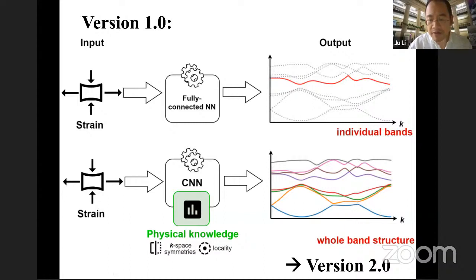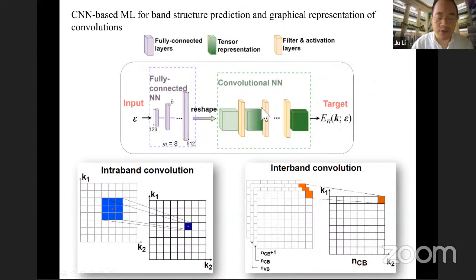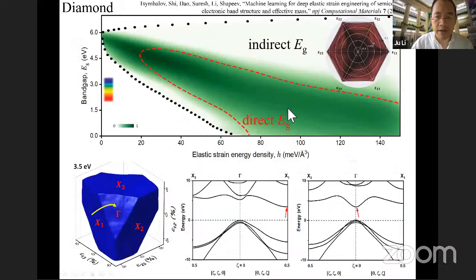And after our 2019 work, we have now extended this work to more powerful neural networks. And we're able to study that of diamond. So you can make diamond from a wide bandgap semiconductor, 5.5 EV band gap, all the way to metal, still staying within the phonon stability range, and you can make diamond a direct bandgap material as well.